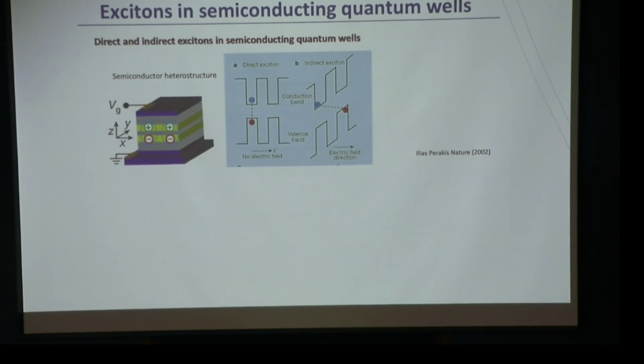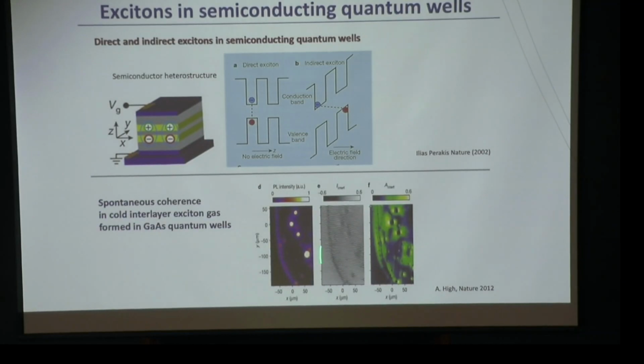And indeed, this is the Butov group's work, which beautifully showed that if you create this interlayer exciton, by pumping the interlayer excitons, they start to see the interlayer excitons develop self-organized coherence in there, which is the very first step of seeing this condensation. Why this is really tantalizing: the development here has been hard.